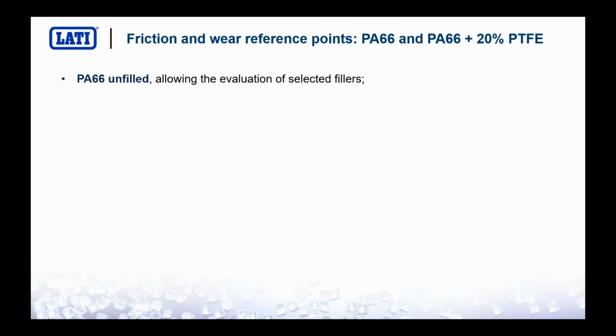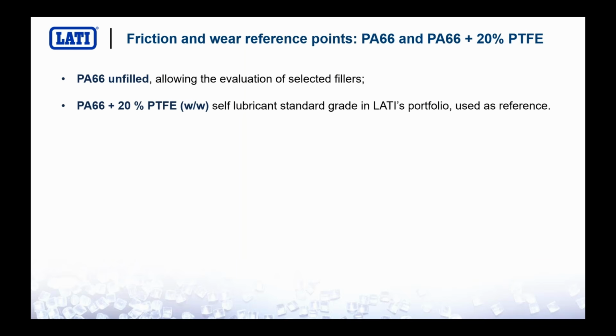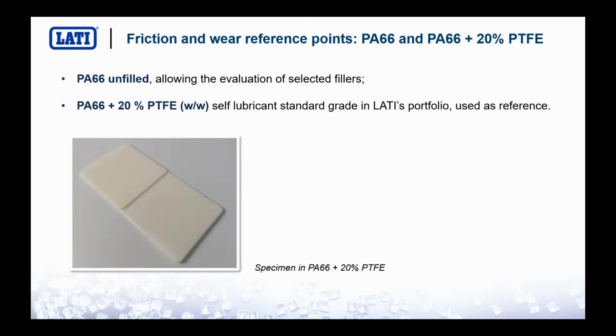As concerns the reference, we started with a material that for LATI is a standard material, the polyamide 66. So we started to evaluate the performances of an unfilled polyamide 66 in order to fix a reference. And then for sure, we also selected a polyamide 66 plus 20% of PTFE, because the aim of this study was to replace it with other candidates. So we use these two materials as reference.